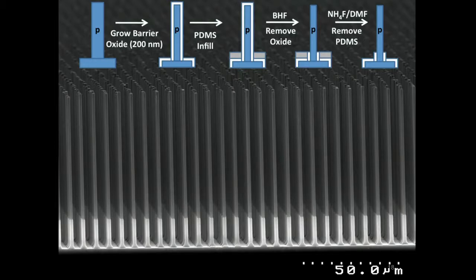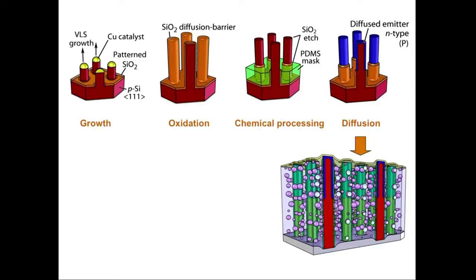These are micro-photovoltaic rods, but not individual, made over massive areas, highly in parallel. And in doing so, and then filling them with scatterers, we can then make a top electrical contact and make cheap, flexible solar cells this way at 1% of the silicon you would normally use. But then if we expose the rods, we can get to our goal of making them useful for hydrogen production.